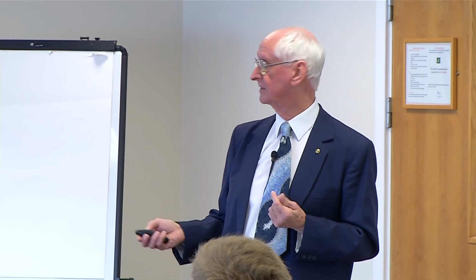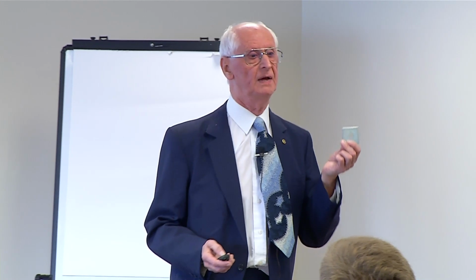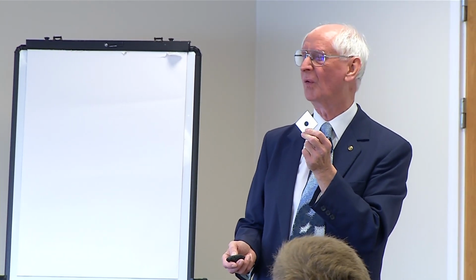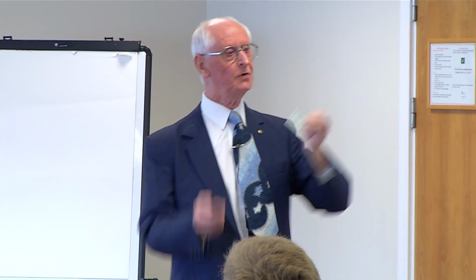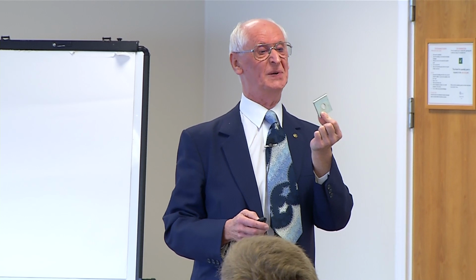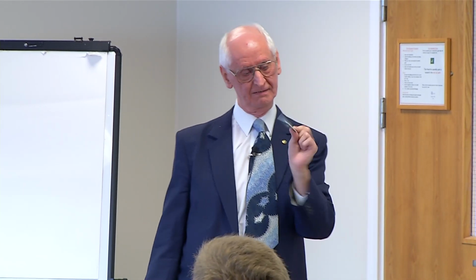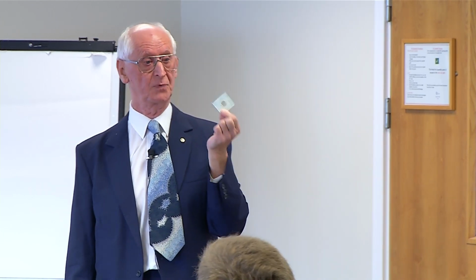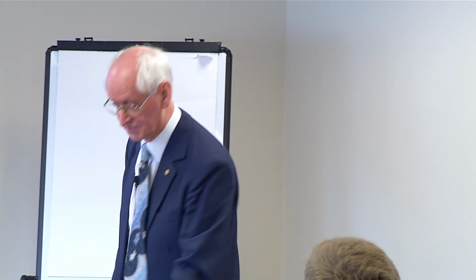You do get things like these washers here, and people will sell them as, oh yeah, that's a galvanized washer. No, it's not. If you press them on it, they will say, oh yes it is, it's electrode galvanized. What a load of nonsense. It's actually bright zinc plated. It's a plating process, and the zinc is very thin and sits on the surface of the steel.